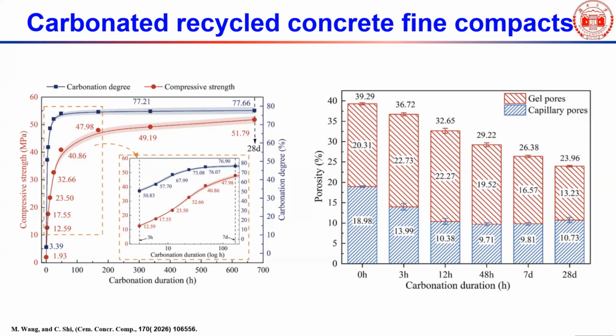Actually, two master's students worked on this. So I said, why don't we just compact the recycled concrete fines to make a product directly? You can see here, after a few hours of carbonation, it reached very high strength, and even a very high carbonation degree. After basically a couple of days of carbonation, it reached almost 70% carbonation degree and strength over 40 megapascal. That's strong enough to make a lot of construction products, right?